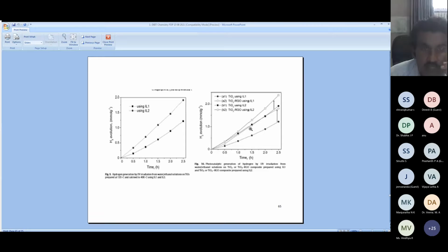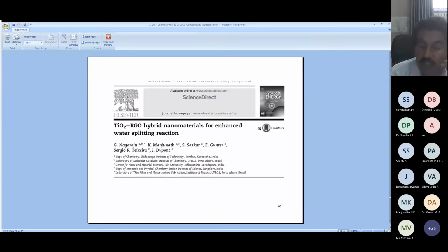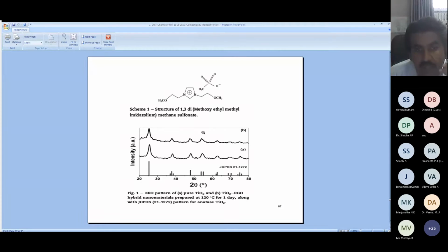Okay, so when you are looking at that, I think I will show you that. Okay, just see here, this is the one at a particular condition we have prepared. This is TiO2 which shows hydrogen generation. For the same material, if you add graphene, yes, there is a huge enhancement in the hydrogen generation for TiO2 RGO. Again here, we have prepared this TiO2 using ionic liquid 2, and it was showing pure TiO2 and then TiO2 RGO. Whatever the materials, whatever the condition, the presence of RGO enhances the hydrogen generation, right? For that, we are going to say that the presence of RGO will reduce the resistivity and increase the hydrogen generation. I think this paper is also going to say the same thing, right?